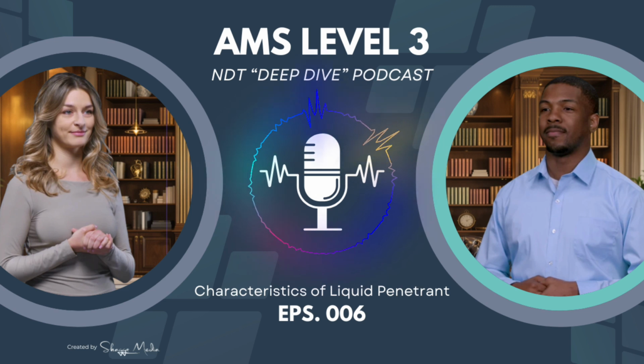This is a really smart technique, especially with hydrophilic systems. Before you even apply the emulsifier, you give the part a quick rinse with plain water. What does that do? It washes away a lot of the loose, gross surface penetrant, sometimes up to 90% of it. This massively reduces the amount of oily penetrant that gets into your emulsifier tank.